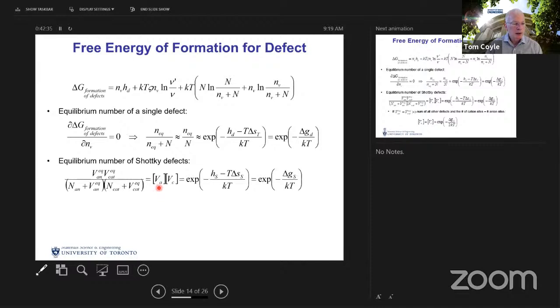The mole fraction of vacancies on anion sites multiplied by the mole fraction of vacancies on cation sites is equal to the exponential of the free energy of formation of that Schottky defect divided by kT. So now we have an equilibrium expression that relates effectively the concentration of cation and anion vacancies to the free energy of formation of that defect. It's important to note that it's the product of these two mole fractions, or atom fractions, which is described in this equation.